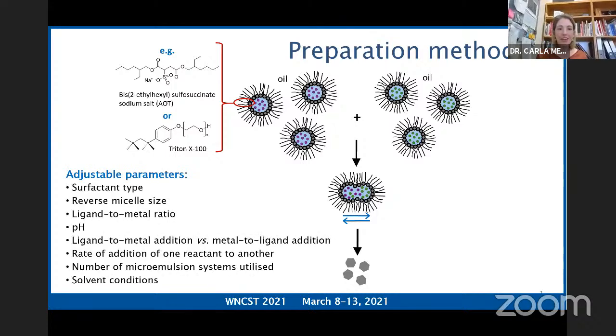As you might imagine, there are really a whole wide range of parameters and synthetic conditions that can be adjusted. Things like the surfactant type, so we can have ionic or non-ionic surfactants forming the reverse micelles. We can certainly control the reverse micelle size, the ligand to metal ratio, so the concentration within these reverse micelles. We can control the pH. We can control the ionic strength. We can control whether we add the ligand microemulsion to the metal microemulsion, or the metal containing microemulsion to the ligand containing microemulsion. The rate of addition of one to the other.